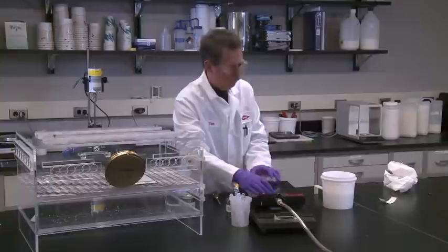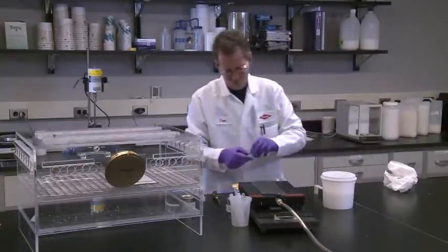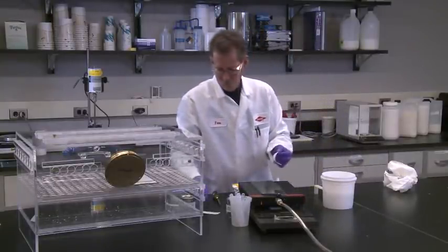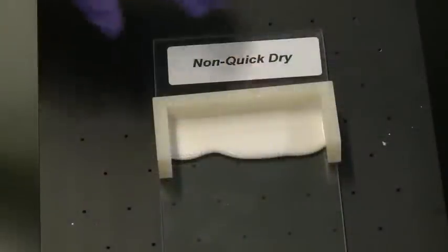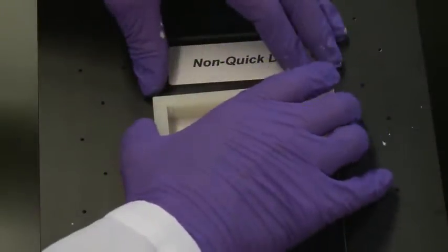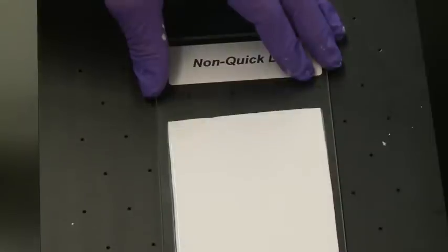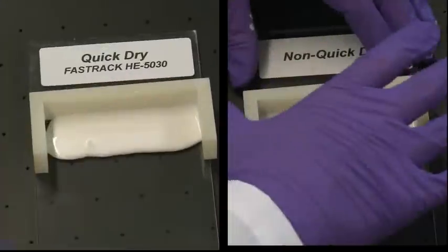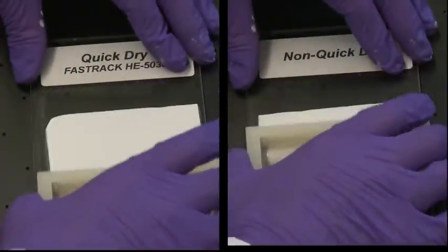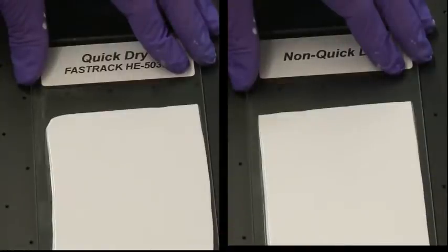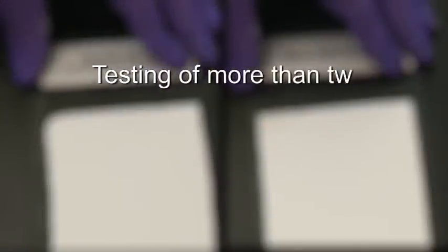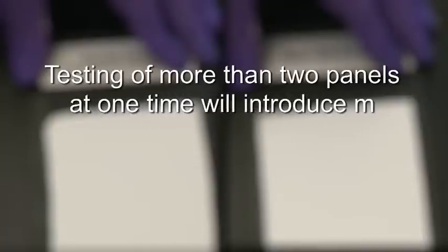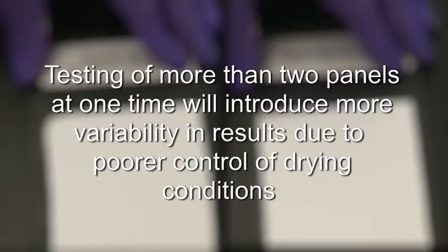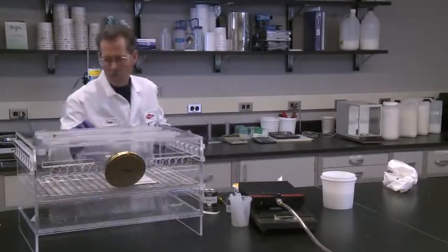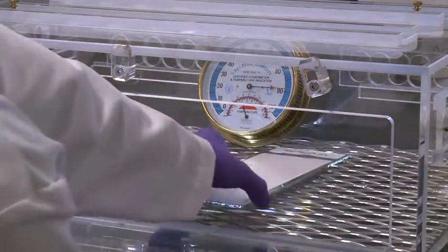Follow the same method to prepare your second drawdown. You want to label each glass panel to keep track of your samples, and you want to use the same or similar 20 mil drawdown blade to maintain a consistent wet film thickness. For most replicable results, it's best to limit your tests to 2 paint samples at a time. Testing of more than 2 panels at one time will introduce more variability in results due to poorer control of drying conditions. Once you've prepared your second drawdown, immediately place it in the test chamber.